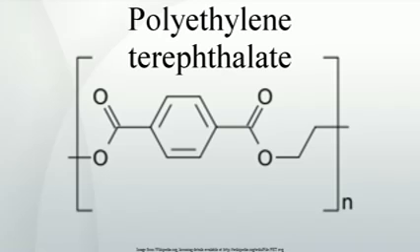An article published in Journal of Environmental Monitoring in April 2012 concludes that antimony concentration in deionized water stored in PET bottles stays within EU's acceptable limit even if stored briefly at temperatures up to 60 °C, 140 °F, while bottled contents, water or soft drinks, may occasionally exceed the EU limit after less than a year of storage at room temperature.